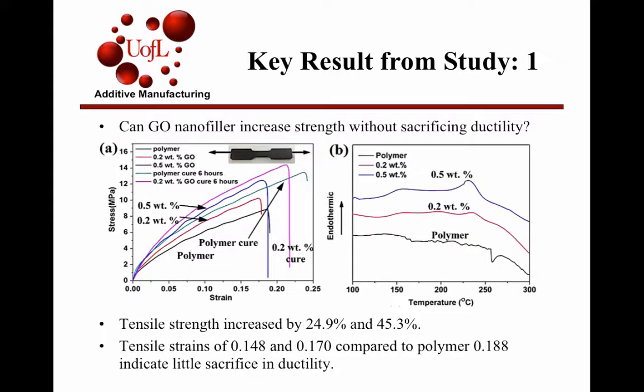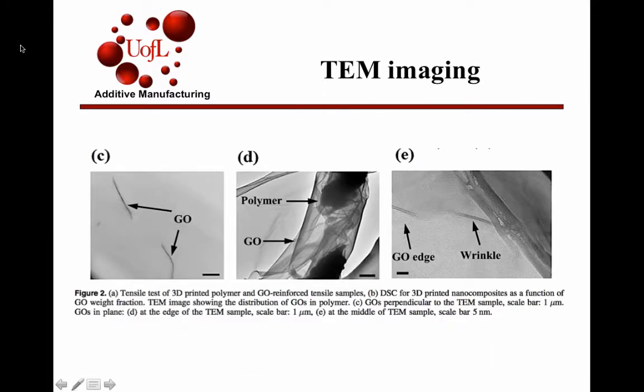This is some of the TEM imaging, and the first one we have here is perpendicular to the graphene oxide. You can see how thin they are. Even when they say perpendicular, they're kind of being generous, because you can't even see it if you get exactly perpendicular to the molecules. You have to tilt it just a little bit so you can get a little bit of a profile, because it's so thin.